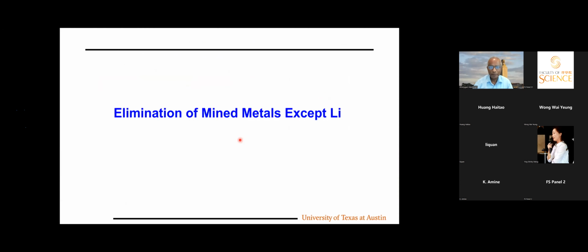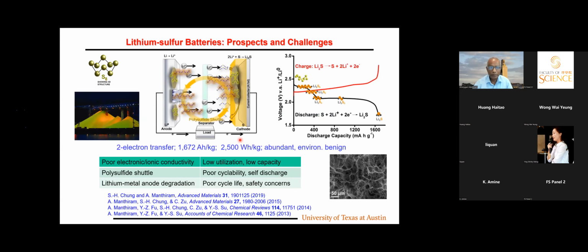Now, those are all so far with layered oxides. Now I'm moving to elimination of mined metals except lithium. So that means lithium-sulfur. Lithium-sulfur has a lot of advantages: 2 electron transfer, huge capacity, abundance, but there are a few problems. Poor electronic and ionic conductivity leads to low utilization and low practical capacity. Polysulfide shuttle again causes poor cycle life, and it also leads to self-discharge.